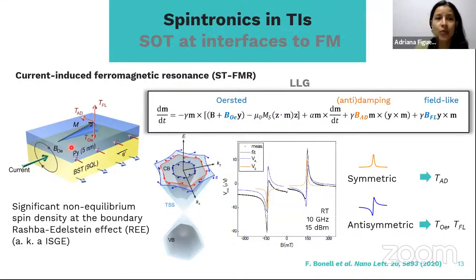This torque can modify the magnetization dynamics on the permalloy, and even reverse the magnetization of that permalloy. So we are also interested in performing magnetic switching in these stacks. And with STFMR, when we analyze the dynamics of that magnetization using the LLG equation, we can identify different contributions to those dynamics.